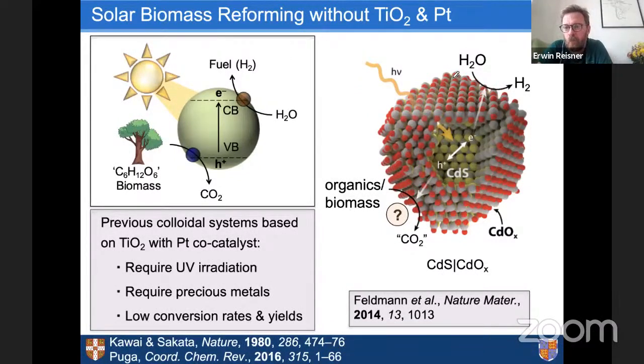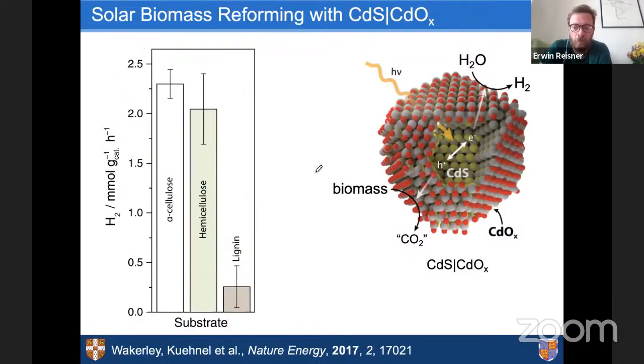And since the Feldmann group also has shown that you can reduce water with this system, we thought, can we just use this as a photocatalyst in an alkaline aqueous solution, reducing protons and coupling this to the oxidation of some organic matter, or ideally even biomass? And to jump straight into it, it worked. We look here at the rate of hydrogen expressed as millimoles per gram catalyst per hour, for each substrate. If we use the polymeric alpha cellulose and hemicellulose, we obtain quite high activities.